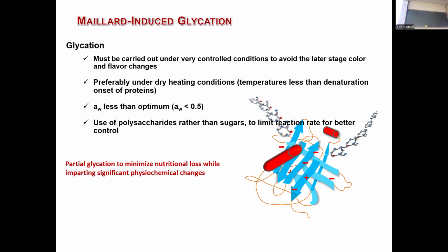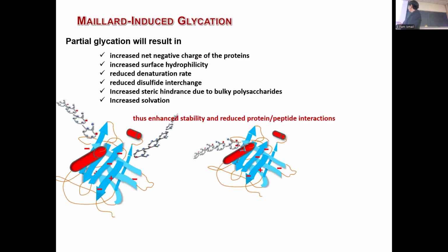So what we usually do, we want to ensure that water activity is less than optimal. Heating is not at a high temperature that would denature the protein, and we use polysaccharides rather than glucose or small reducing sugars. And we want to partially glycate so that not every lysine is glycated, because excessive glycation might cause gelation, not enhance solubility. So basically when we glycate, we block a positive charge, so you're increasing the net negative charge. And the increased net negative charge and the relatively large carbohydrate will enhance surface hydrophilicity. And then we will have less denaturation, less disulfide interchange because of steric hindrance, and increased solvation, meaning interaction with water.